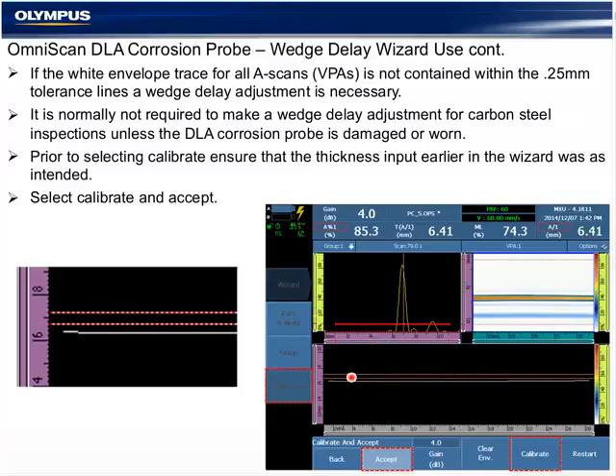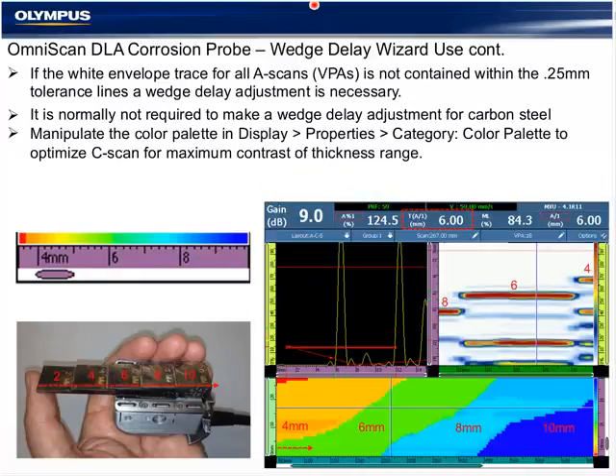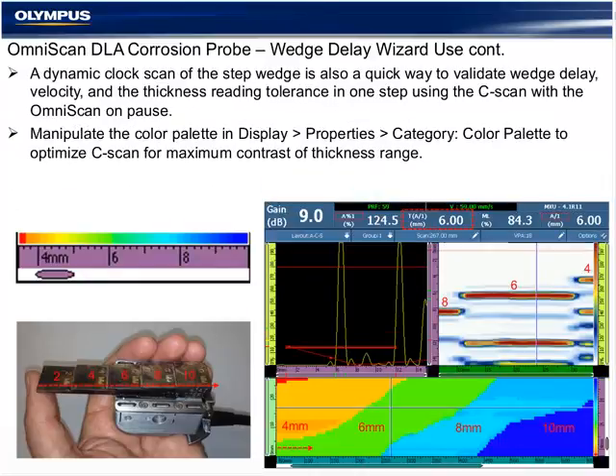You should suspect some other problem - maybe the stabilization guide is not adjusted properly so that the probe is directly in contact well with the component. Under normal circumstances, we would not normally need to reset the wedge delay if the wedge is not damaged or worn beyond light scratches. So we would select accept, create our green checkmark, and the wedge delay is validated.